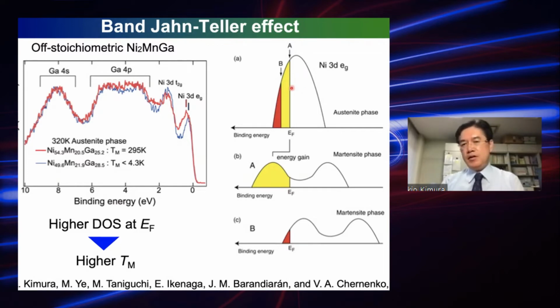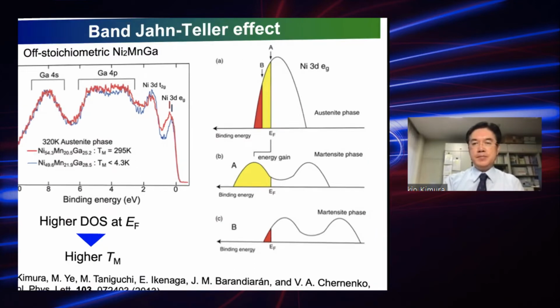On the other hand, when you have the Fermi energy just at the tail of this density of states, the large energy gain is not so much obtained. This result tells us that the Fermi energy position is also very important.